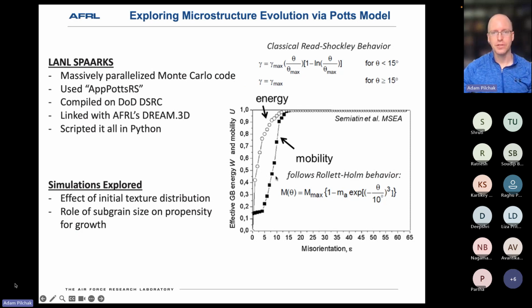I think everyone remembers the classical Read-Shockley behavior plot, which shows grain boundary energy as a function of misorientation. Small angle grain boundaries have relatively low energy, and therefore relatively low mobility. For FCC metals, it's pretty well established that by the time you get to about 15 degrees misorientation, energy becomes nominally constant, except for certain special grain boundaries, sigma 3s and things which aren't represented here. Since we were seeing this metadynamic recrystallization process that seems to be driven by subgrain misorientations and how that impacts their mobility depending on the grain boundary energy, we pursued using the SPPARKS code from Los Alamos National Lab.